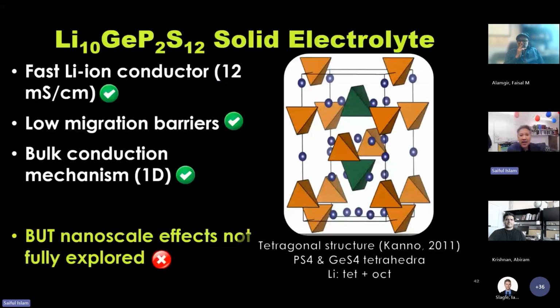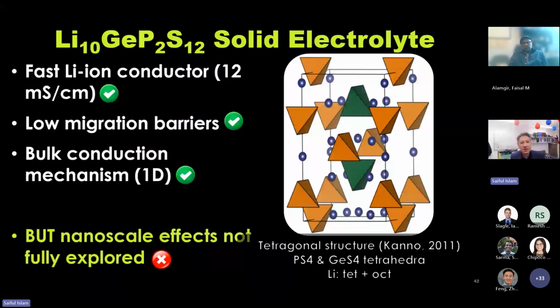This is the classic LGPS, lithium germanium thiophosphate. The reason why it's classic is that in 2011, Kanno in Tokyo, Japan, found that it was an exceptional fast lithium-ion conductor, 12 millisiemens per centimetre, which is really exceptional for a solid-state material. Low migration barriers, about, I think, 0.2 electron volts, and the bulk conduction mechanism was 1D. This is the structure on the right.